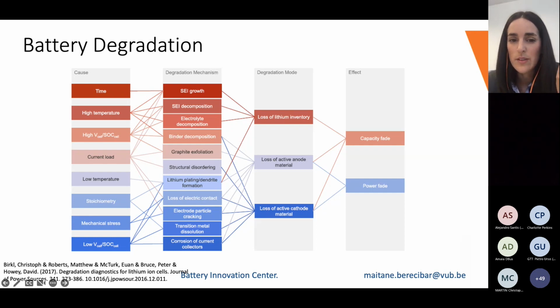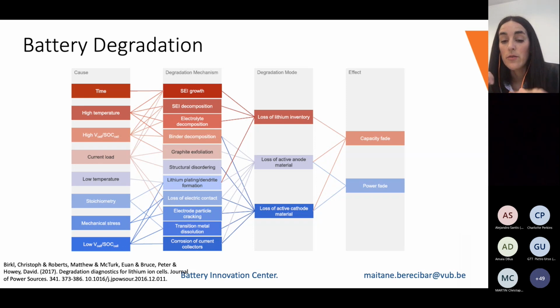But of course, what we need to understand is why these degradation mechanisms are happening. Because of different causes: because of current load, because of low temperature, because of mechanical stress on the battery. So these are the different causes that at the end create those degradation mechanisms. We will need to use the batteries in the best way within some limitations, but of course we will need to try to stop these degradation mechanisms as much as possible, or try to reduce their magnitude, or try to make them slower in time. So for this, there are possibilities.